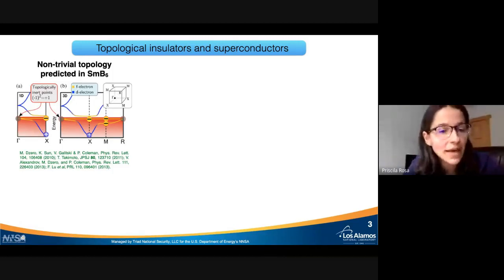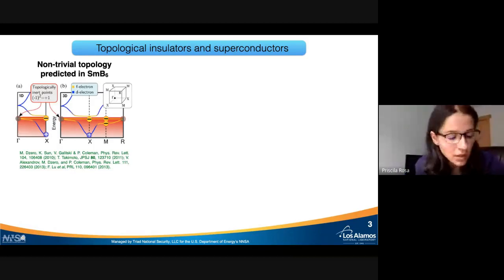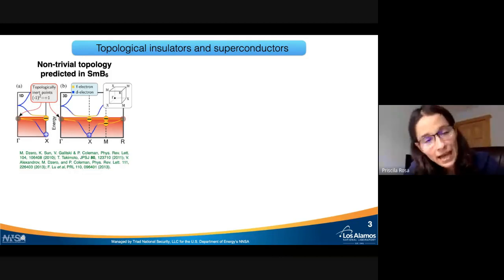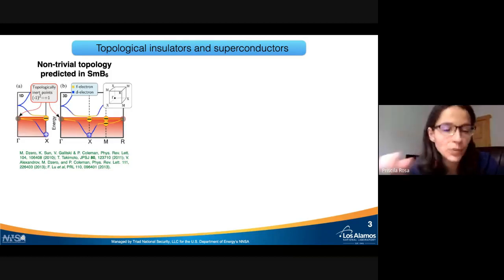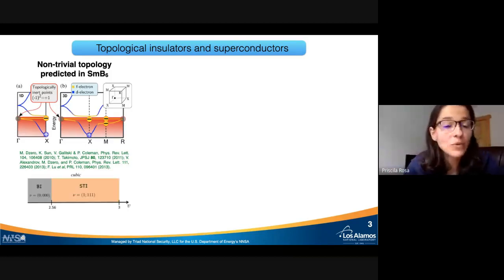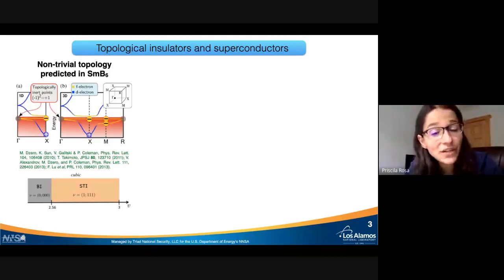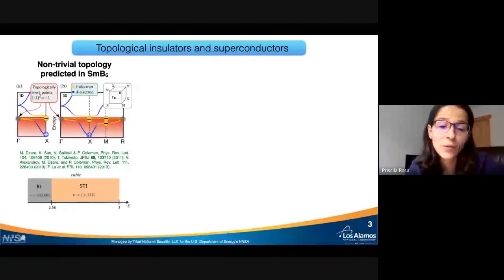And this happens because at the X point of the band structure, there is what I was referring to in the previous slide, an inversion of the bands. So the parity there is inverted. If you calculate the parity at the X points, you're going to get a -1 sign, and this should be a topological insulator. One perhaps side note is that it's interesting that one can tune this material from a band insulator, so a trivial insulator, to a topological insulator by changing the valence of samarium. Samarium can be either 2+ or 3+, and we're going to see in just a moment that in this material we actually have something in the middle.